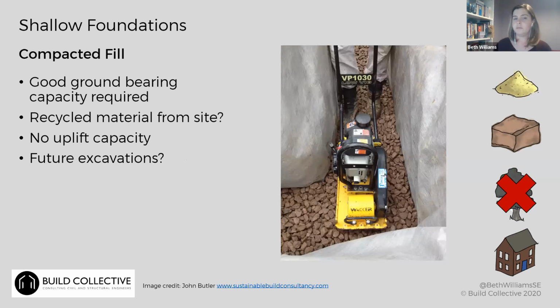Another option of shallow spread foundations, where the concrete compressive strength isn't the governing design criteria, is compacted fill trenches. So in the same way that you would add fill underneath a ground bearing floor slab or something. Again, as with masonry spread foundations, I wouldn't recommend these for deep trenches, because you've got to get in there and you've got to compact the fill. But you want an even loading profile around the perimeter of the building to avoid differential settlement.